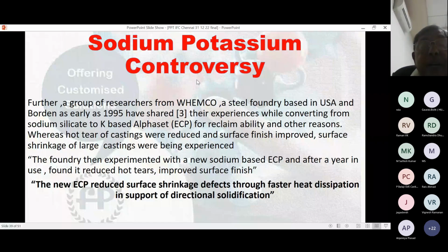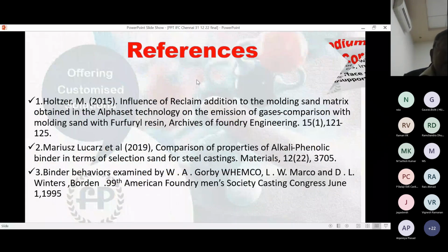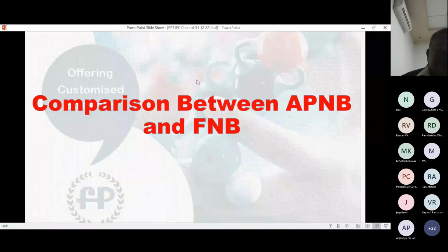The foundry then experimented with a new sodium based ester cured phenolic, and after a year in use, found it reduced hot tears and improved surface finish. The new ester cured phenolic reduced surface shrinkage defects through faster heat diffusion in support of directional solidification. This is not my word. This is recorded, and these are the three references I have given. You can cross check from the literature. So now the final phase, your comparison.